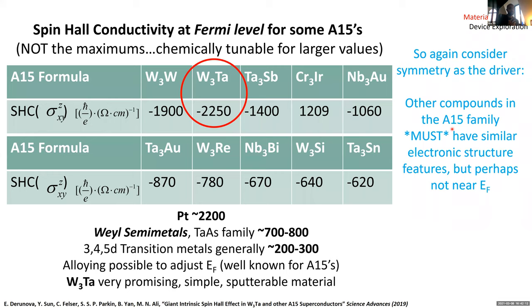So we looked at various other materials in the A15 family. That's the name of the crystal structure. And we found computationally that there were a variety of other good candidates that had large spin Hall effects comparable to platinum and to beta tungsten. And that with a simple alloy, in order to move the Fermi level basically down onto that peak in the spin Hall connectivity, an alloy with tantalum should actually help us get a little bit higher, maybe 10, 20% higher. So we decided to take a look.